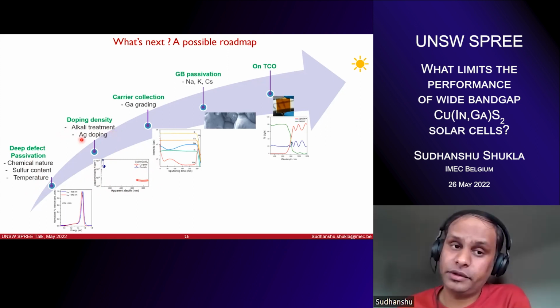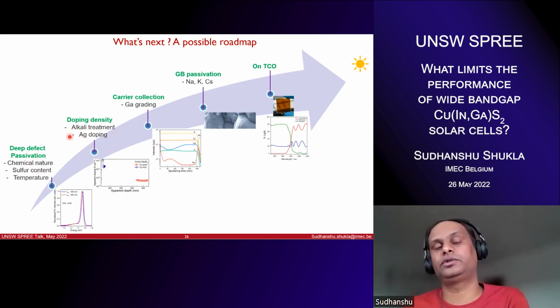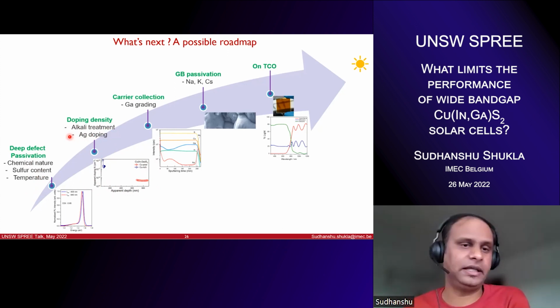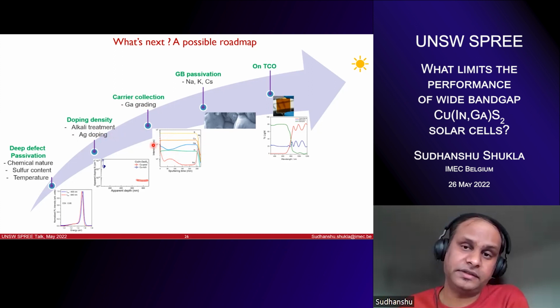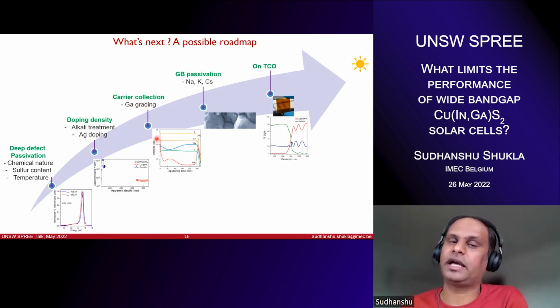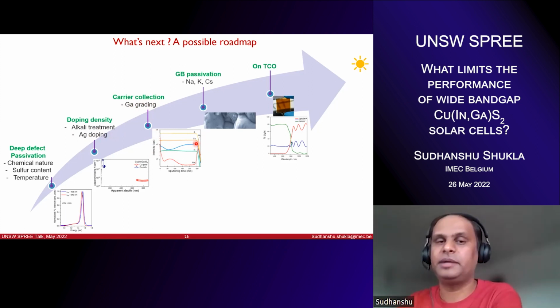And also silver doping, for example, that is showing quite encouraging results in kesterites and also for selenides by reducing the band tailing, which is not limiting here, but it does play with the doping density as well. So it could be useful. Then these gallium gradients to improve carrier collection. And this is also something that has been extensively done for selenide absorbers, but not much do you see on the sulfides. So I think gallium grading is also something that will come at one point that can be improved.